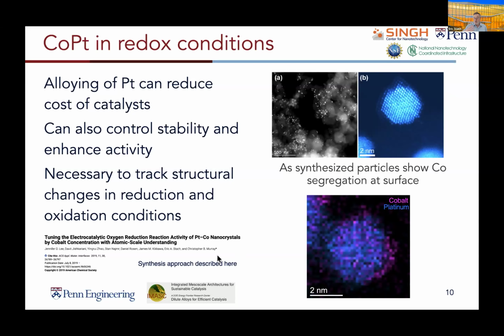Using the electron microscope, this is just simple imaging before the reaction. You can see that these particles have a very faint contrast on the outer surface, and that's because the cobalt, which is much less heavy, is scattering less strongly. So we see that upon synthesis, these have a relative cobalt segregation at the outer surface. And that was true for really all the particles that we were looking at before the reactivity occurred.